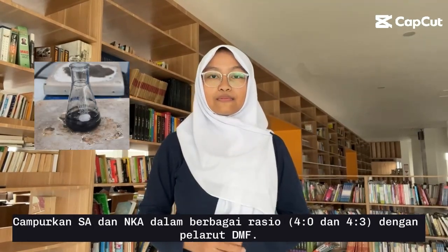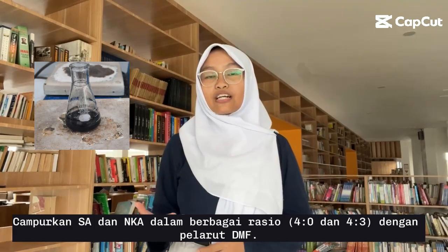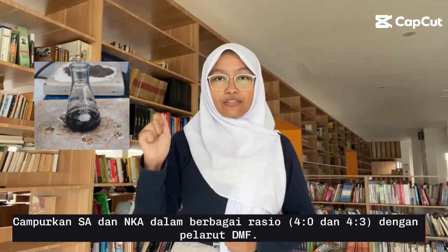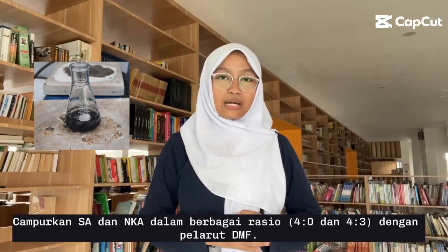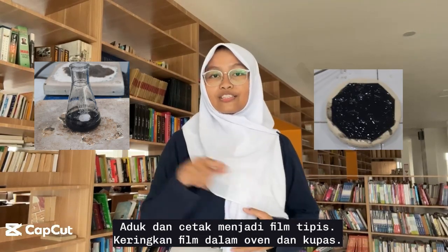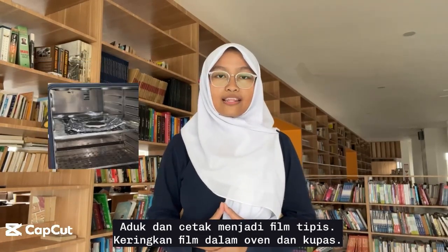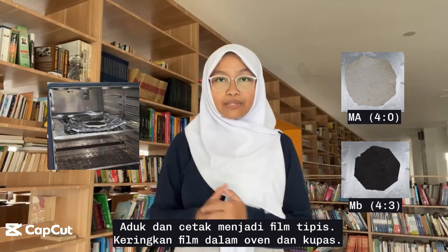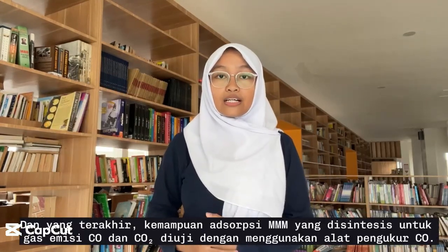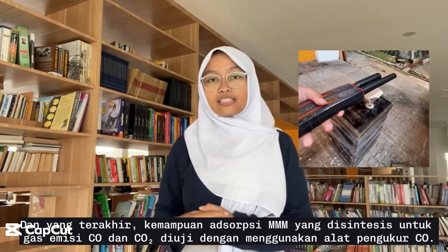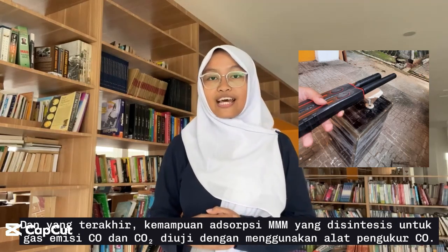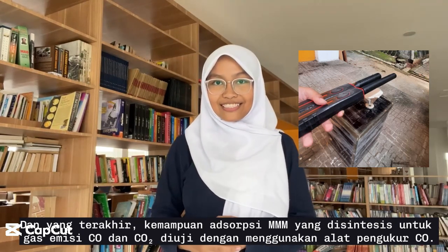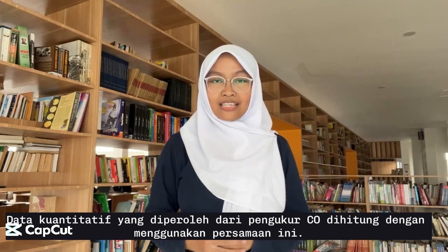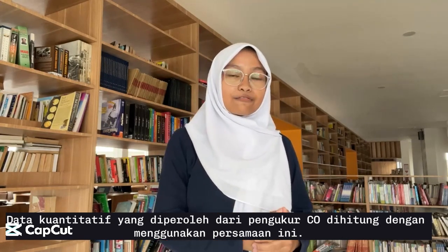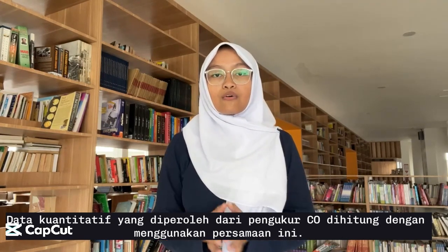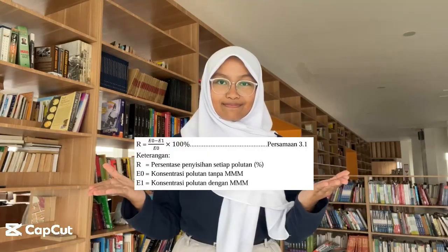And the next one is to mix the cellulose acetate and nano-activated carbon in the ratio of 4:0 and 4:3 with DMF solution. And the next one is to stir and cast into thin films. And then dry the films in an oven and peel them off. And the last one, the absorption capability of the synthesized MMM for CO and CO2 emission gases was tested using a CO meter. And then, the quantitative data obtained from the CO meter was calculated using this equation.